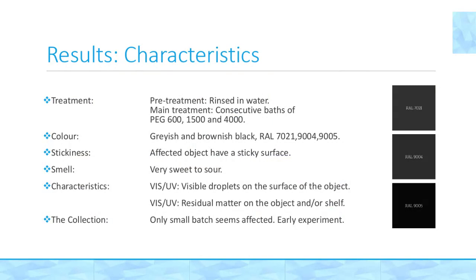Here I have summarized the similar characteristics that I found in these objects. The objects share a similar treatment method. They were first rinsed in water, and then they were treated first with this shorter chain polyethylene glycol, that's a PEG 600, and then either PEG 1500 or 4000, so a longer chain. They shared a similar color. Most objects could be called grayish and brownish black, or more specifically, RAL colors 7021, 9004, and 9005. All objects had a sticky surface when touching them, and when smelling the objects, most of them smelled extremely sweet. Only those objects which had been stored in those little plastic bags smelled very sour, so I assume that this might have something to do with being stored in a microclimate.